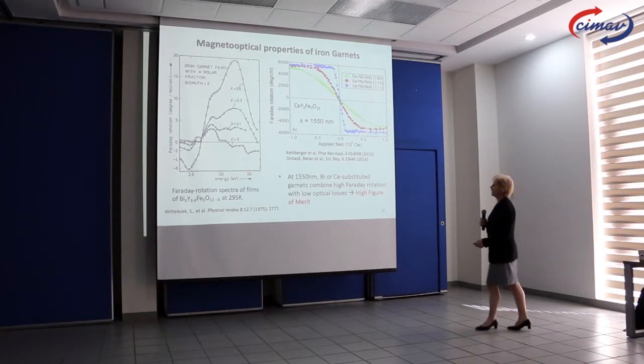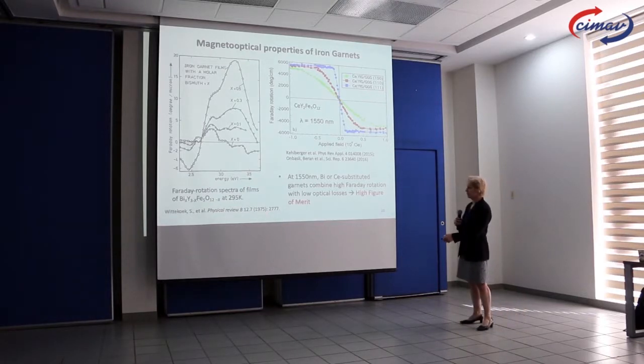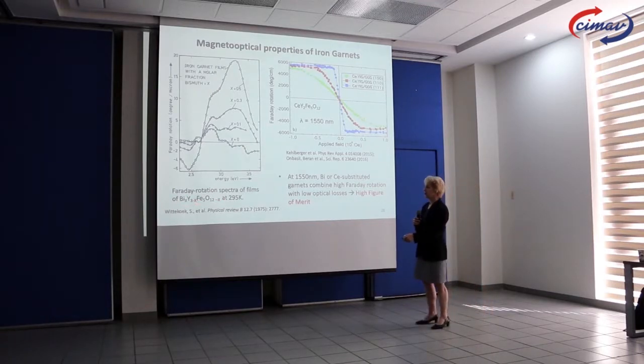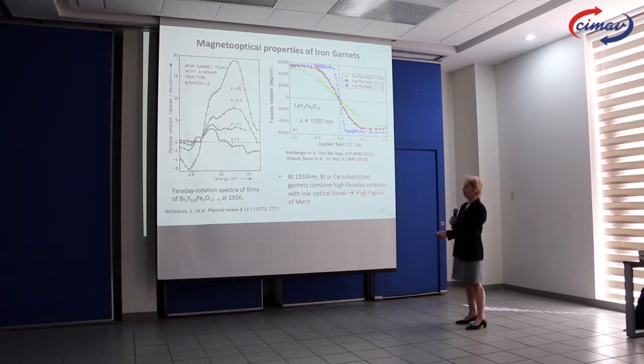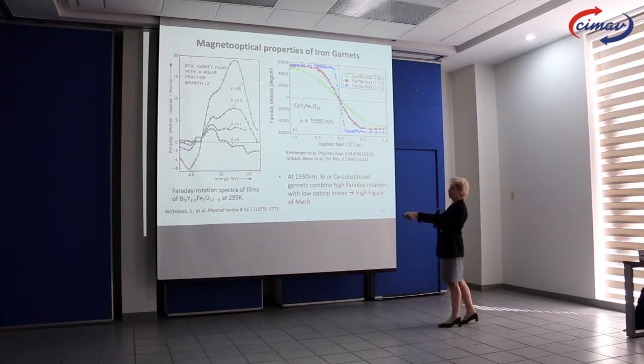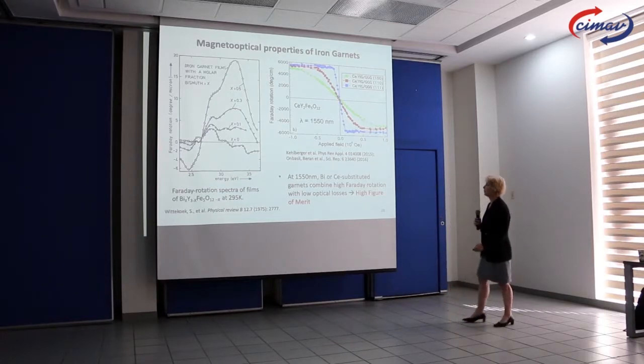Okay, so it turns out that for years and years, this is back in the 70s, it's well known that bismuth garnet, bismuth YIG, is a good material for Faraday rotation. It's been very well studied, and this is the effect of the photon energy. The ones we're interested actually are off the bottom here at 0.8 eV, is where we care about.